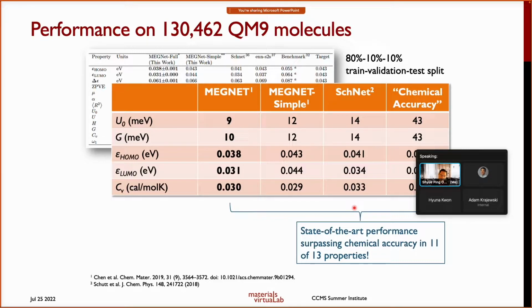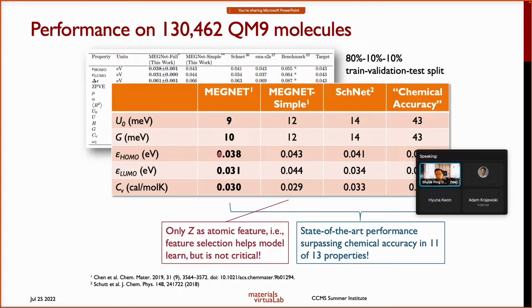There have been models since that have further improved upon this performance, but by and large, this performance is already extremely good, and it is well within what chemists generally consider chemical accuracy. For example, for things like the internal energy, the Gibbs free energy, the HOMO and LUMO levels, and the heat capacity, you can predict the properties of all these molecules to a very high degree of accuracy, right? Now, you will notice that there is one called MEGNet and the other called MEGNet Simple. The difference between the two is that in this particular model, we use a very complicated set of input features based on things like the aromaticity of the bonds as well as the electronegativity of the atoms and so on and so forth that were used in this SchNet model.